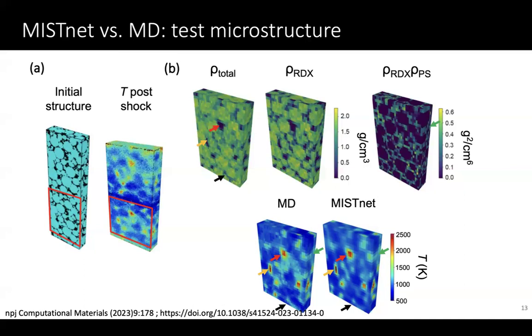And we did a lot of testing of the ability of the network to predict pores that it hasn't seen, and the performance is truly remarkable, okay? With a speed up, that's 10 to the 8, the computational cost. After training, 10 to the 8 speed up compared to the molecular dynamics simulation.